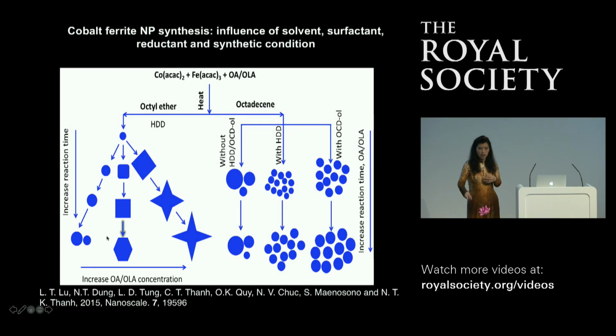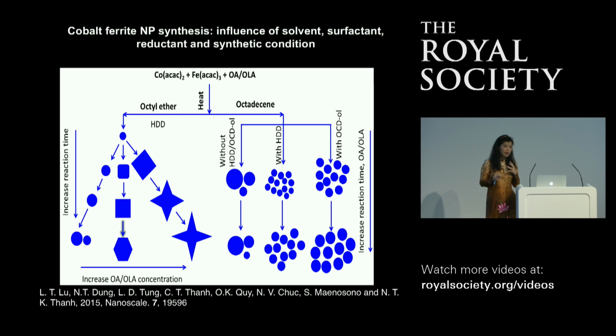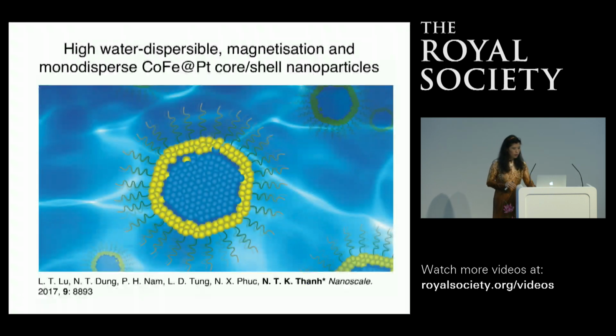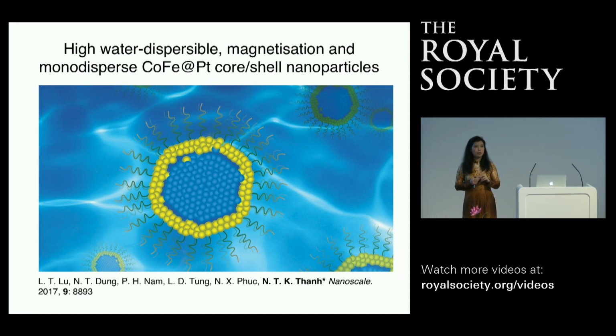But also, you look at the reaction time. It depends on the reaction time, and also on the different amounts you are adding in. So you can see that we are busy, many of us working in the lab and making different things, because there are so many different parameters we need to look at. Knowing the physical property we require, we go back to chemistry and find the nanoparticle we want. If you remember on the table, the iron cobalt alloy has a very high saturation magnetization, 235 emu per gram. So we aim for that.